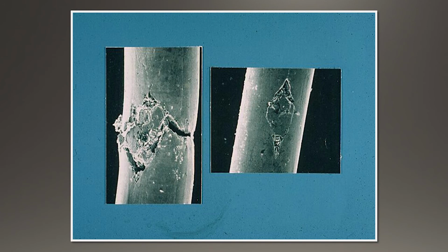Here's an example of an inclusion. The inclusion on the right is small enough so it hasn't caused the break. Once again, if the inclusion is too small, you may not get a break until it's a smaller size wire. And in general, when the inclusion reaches approximately 25 to 30% of the cross-sectional area, then you'll get a wire break. In the picture on the left, that's a wire that's just about ready to form a wire break. You can see the inclusion and there are cracks surrounding it.